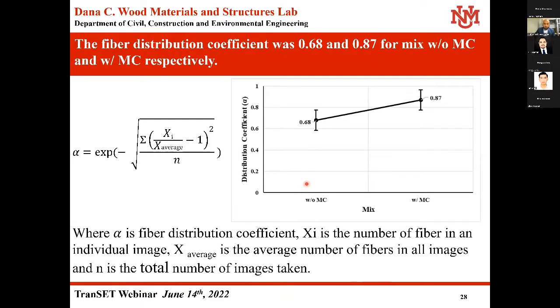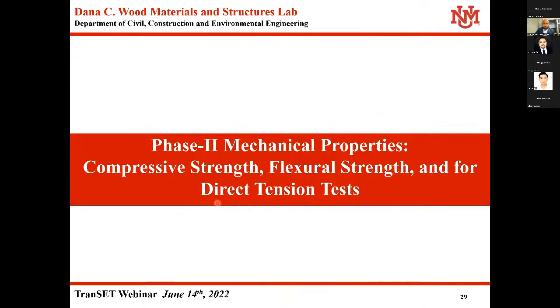To confirm it, we also measured the distribution coefficient. In case of mixes without MC, the distribution coefficient was 0.68, but it increased to 0.87, which shows a better dispersion of fibers with the addition of methyl cellulose. And this is another reason why we get better quality in terms of buildability, extrudability, and shape retention.